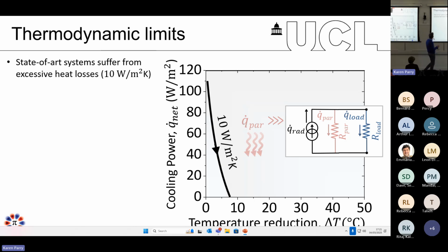So for the vast majority of the systems that have been presented so far, the parasitic heat losses are very high. They're usually represented by what we call thermal transmittance, the same as in any insulation system. And the thermal transmittance is typically on the order of 10 watts per meter square Kelvin, which means that the equilibrium is at under 10 degrees. So most of the systems in the literature can go up to 8 degrees below ambient.